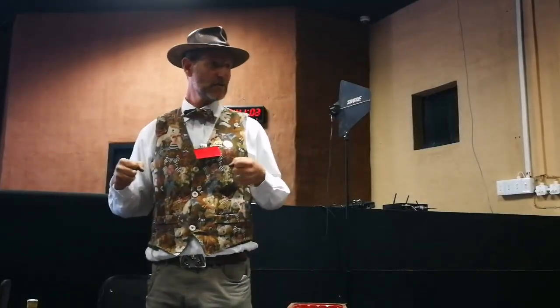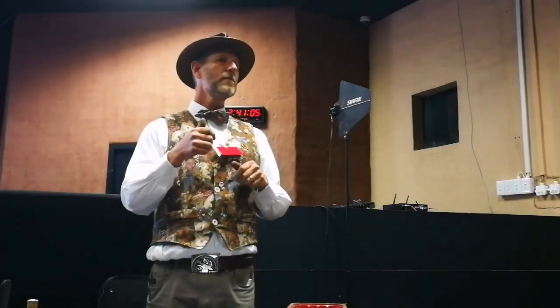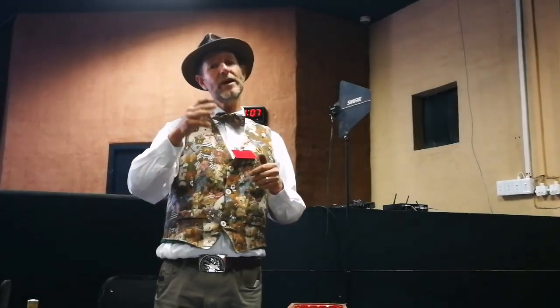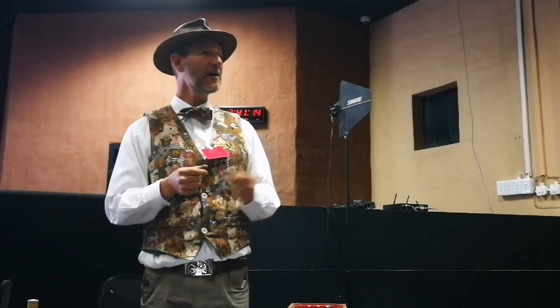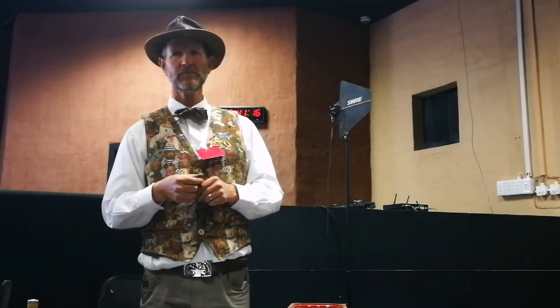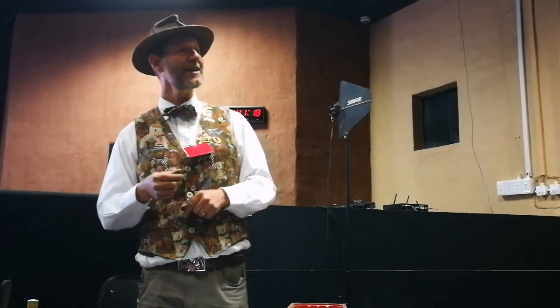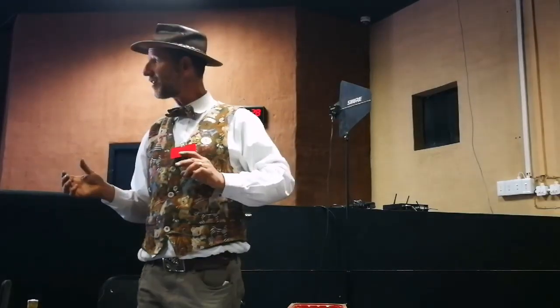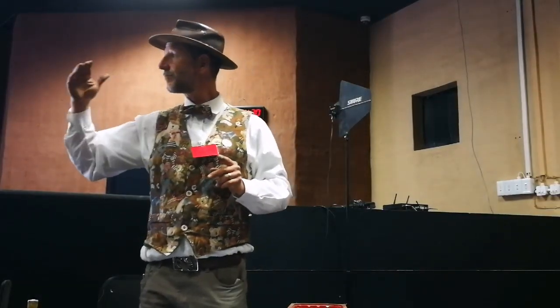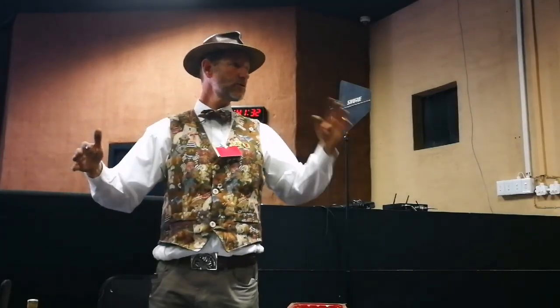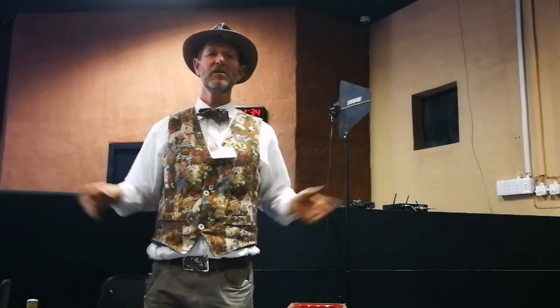So there's a high level of ductility. But on the other hand, when that 5160 is quenched and comes out of the oil, it exceeds your required hardness for a hunting knife by about 2 or 3 Rockwell. It comes out of the oil harder than you want anyway. So when you temper your steel, by either tempering it back just a little bit or a great deal, you can land up with a whole spectrum of hardnesses, right from hunting knife hard to sword flexibility and anything in between.